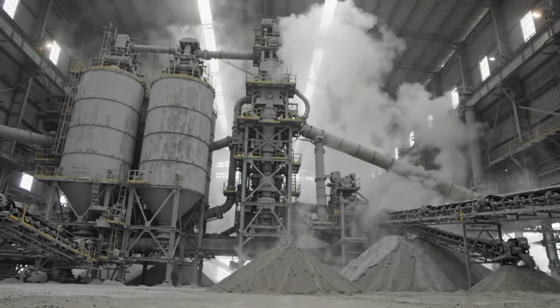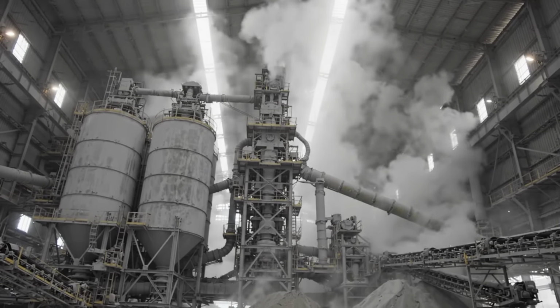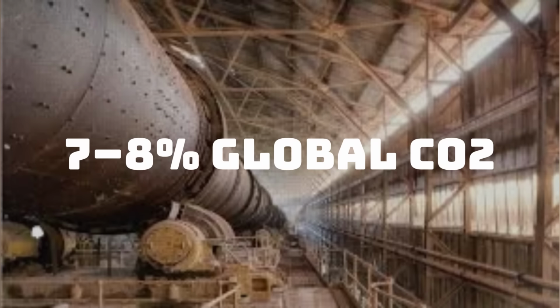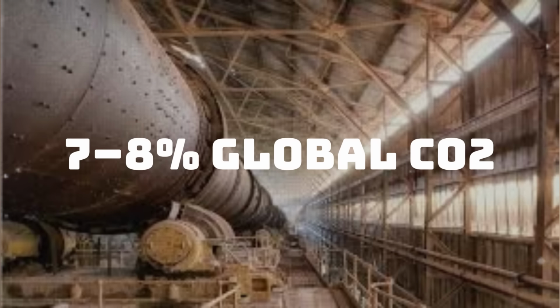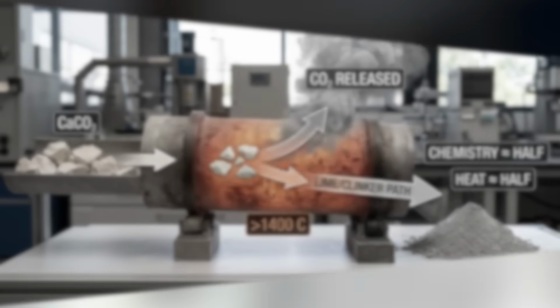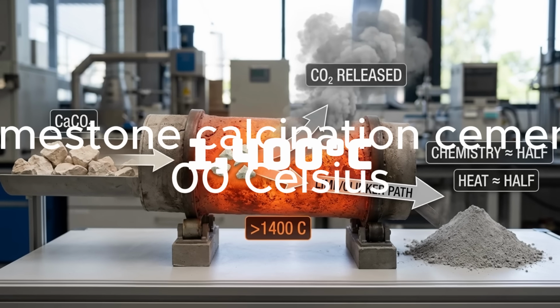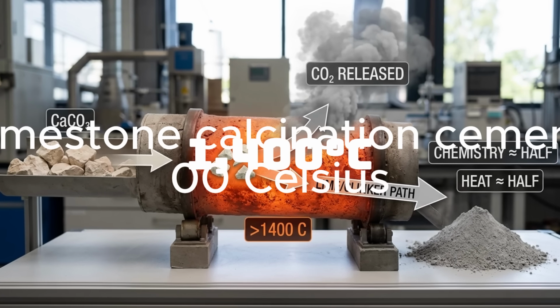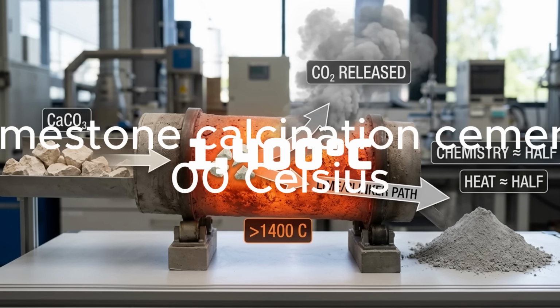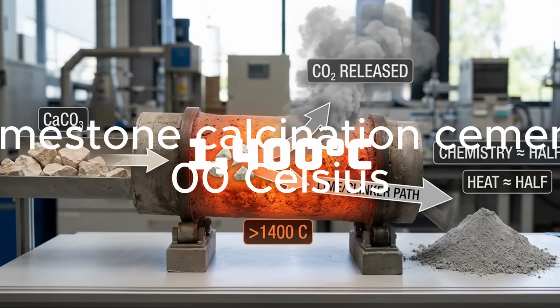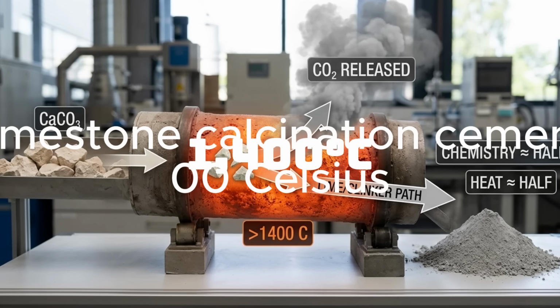But economic optimization comes with costs the original engineers never had to count. Modern Portland cement production accounts for roughly 7 to 8% of global carbon dioxide emissions, about 1.6 billion metric tons of CO2 in 2022, with a trajectory toward 3.8 billion tons per year by mid-century. Roughly half of those emissions come from chemistry. When limestone is calcined at over 1,400 degrees Celsius, it releases CO2 as a stoichiometric byproduct, regardless of how clean the energy source is. The other half comes from the heat itself.